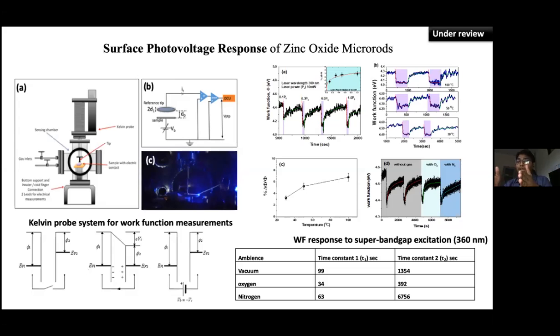So in the process, when this electron hole pair is generated, you can see that the electron is already in the n-type crystal, where there is already an excess of electrons. So it is very unlikely for the electron to recombine with the minority carriers, but it is very likely that the hole which is generated can annihilate with one of the majority charge carriers. So one can actually look into this. The signal which is not recorded by the electronics is basically the signal which is trapped in the surface states.